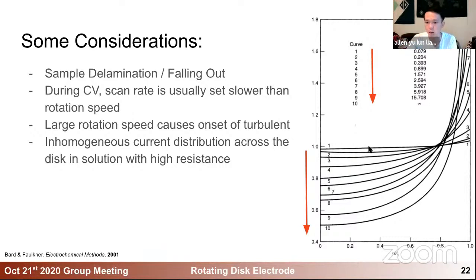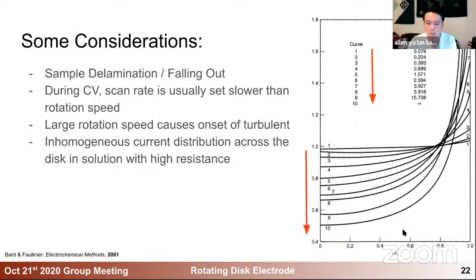In curve number one, you would see that the current distribution across the disk from the center to the outer part is pretty much even. However, once you go to larger and larger electrolyte resistivity, you will find the current distribution getting more and more inhomogeneous. That is something you have to consider, whether that will affect your material performance, or you will be activating only a small portion of your material, while the other portion of material near the center will not be reacting at all.